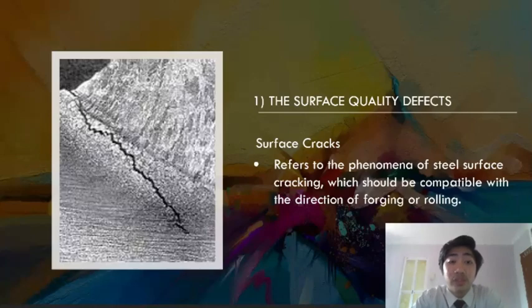Surface cracks refers to the steel surface cracking phenomenon. Generally it should be consistent with the direction of forging and rolling. Reason: the hairline cracks, hot cracks, and cool cracks are mainly caused by excessive surface burn, decarburization, loosening, deformation, and excessive internal stress in the processing, forging, rolling, heat treatment, and tempering, and too much surface impurities such as sulfur and phosphorus.